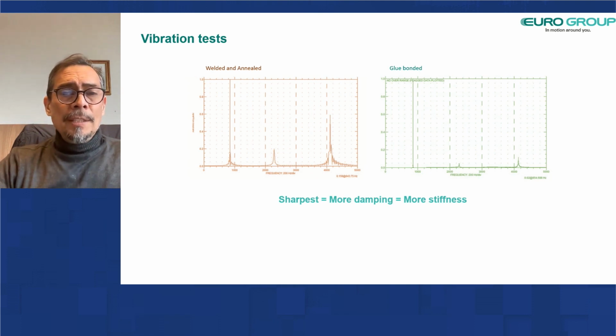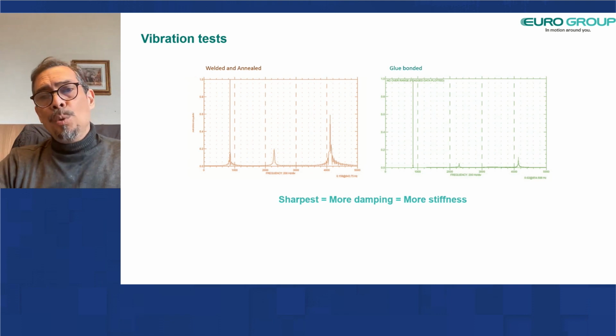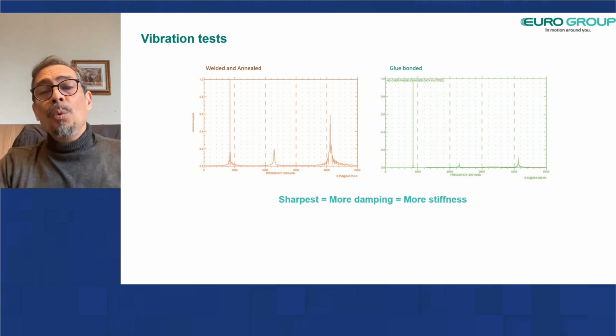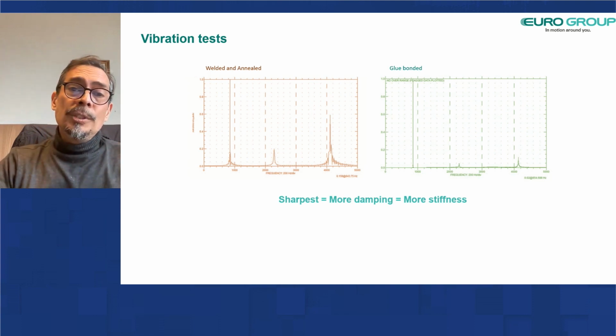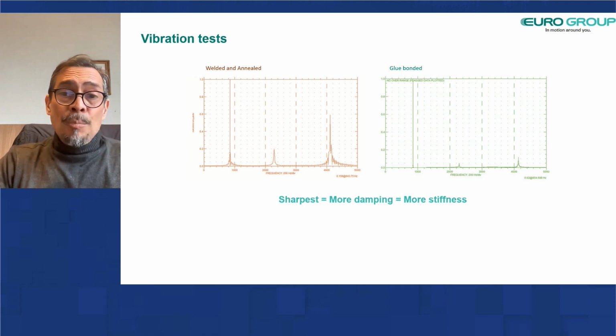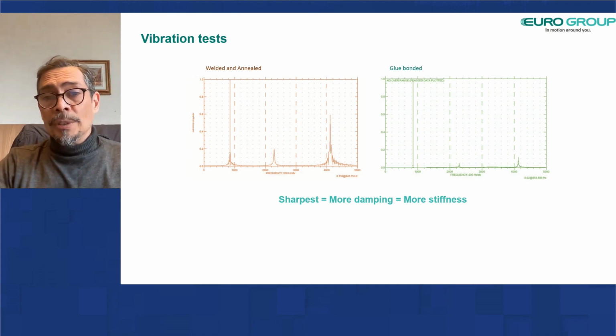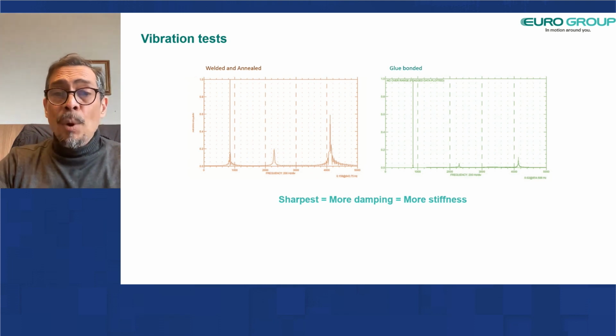This is a typical vibration test in a free setup with the hammer technique, and you can see on the left side that you have three modes of vibration that are shown with the product that was welded and annealed. And once you take the same product and you glue bond it, removing the weld beads and removing the annealing for that matter, you see how the vibration disappears very much, like it is reduced more than 20 times. You still have the same mode of vibration because it is the same geometry, but the amplitude of the vibration and also the sharpness of the vibration is very much reduced.